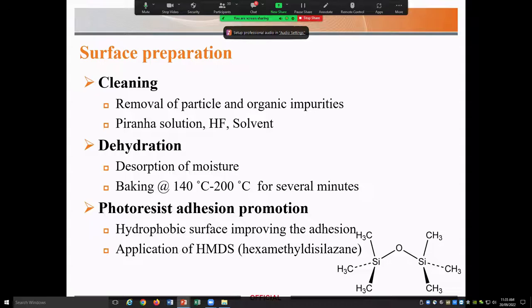Dehydration. The adhesion of photoresist can be negatively affected by the moisture content on the surface. That's why in some lithography processes, we may need to bake the substrate prior to coating to enhance the photoresist adhesion. And still, some photoresists tend to have poor adhesion to some types of substrates, and that's where we use primers prior to photoresist coating. A very common one is HMDS, which makes the surface more hydrophobic and can enhance the adhesion.